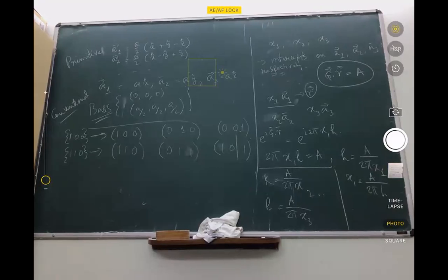So first of all, this H, K, and L, they do not have a common factor. So that already gives you a unique direction in the reciprocal space, in terms of the reciprocal lattice vector, and that tells you which family of planes you are talking about. That uniquely defines it. So if you have two different sets of Miller indices, they would mean two different families of lattice planes. Okay.